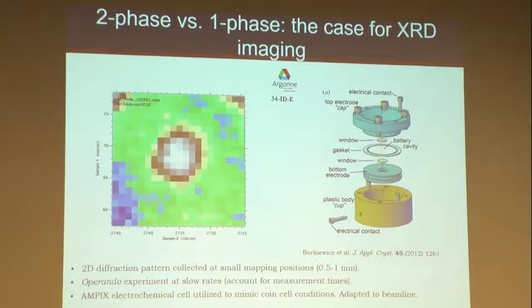This was done at 34-ID-E. This is the Ampix cell that a lot of you probably know. It was modified so that we could map with a sub-micron beam different spots in a particle and get a diffraction pattern of every spot. This was done with a monochromatic beam and an image plate detector on the back. So we're getting powder rings and integrating those rings.